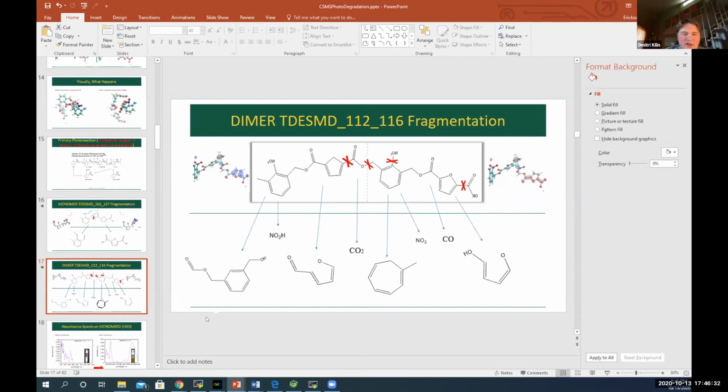And in the simulation, it would correspond to taking the shorter part of the trajectory. So indeed, for this pair of orbitals that you are indicating with blue and red, the reaction seems very vivid, and it decomposes into a lot of fragments in a short time. But I'm afraid, or I foresee, that the organic chemistry audience may doubt that decomposition of a polymer, the cleavage of so many bonds, is realistic.